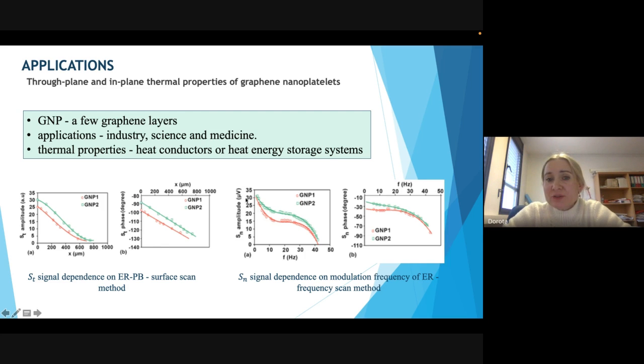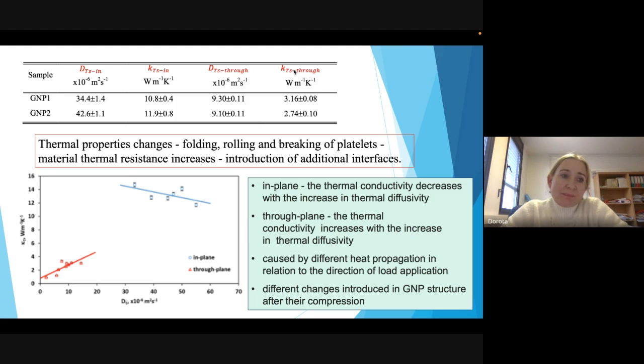To get the values of through-plane thermal properties, we must use the so-called frequency scan method. So we collect the signal as a function of modulation frequency of the excitation radiation. This is what I emphasized at the very beginning, that by changing the modulation frequency, we can change the depth from which we collect the signal, from the very subsurface layer to the bulk material. So the sample we analyzed was loaded with different pressures because we wanted to see how the thermal properties, the in-plane and through-plane thermal properties, change after such loadings. So what we received is that the character of changes depends on the direction we are analyzing.